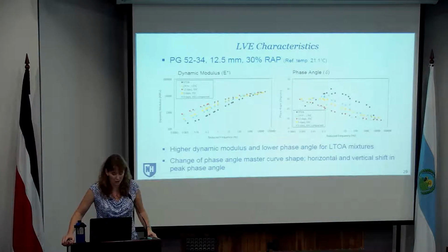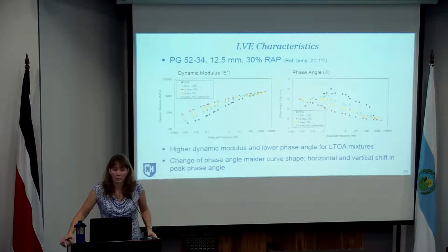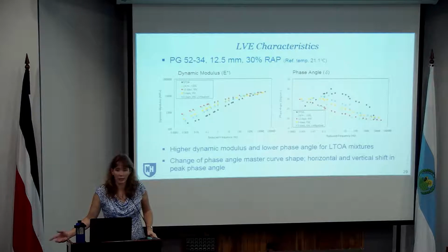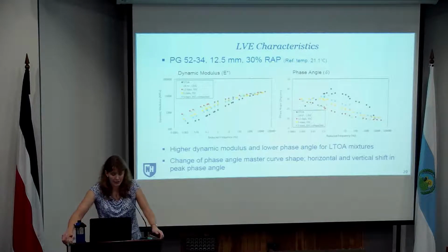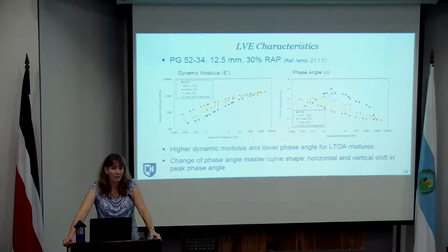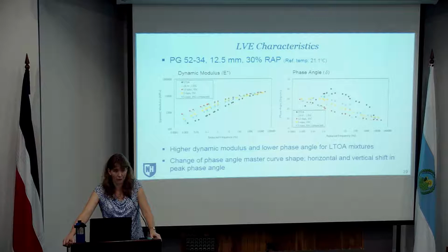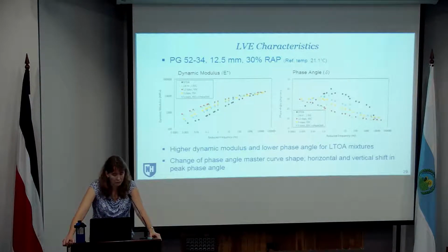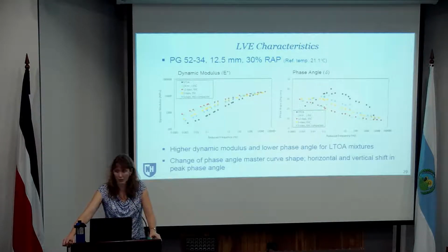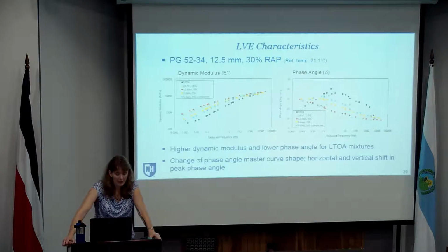So the short-term condition, which is the black dots, those were the mixtures that were sampled right out of the plant. They were reheated for the purposes of fabricating specimens, but no additional conditioning was done. And then the blue X's, those are the materials that were compacted and then aged in a compacted state for 5 days. Then we've got the yellow points. Those were the 5 days of aging in the loose condition at 95 degrees C, which were then compacted. And then the red is the 12 days at 95 degrees C in the loose condition, and then the green is the 24 hours at 135 degrees C in the loose condition.